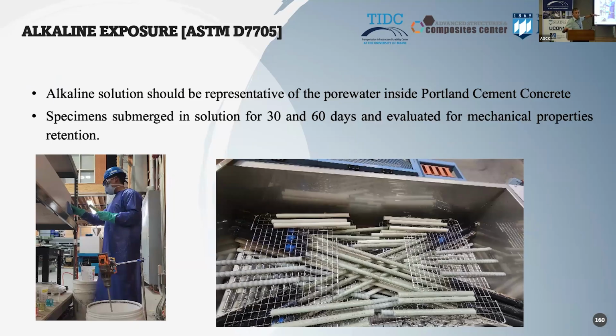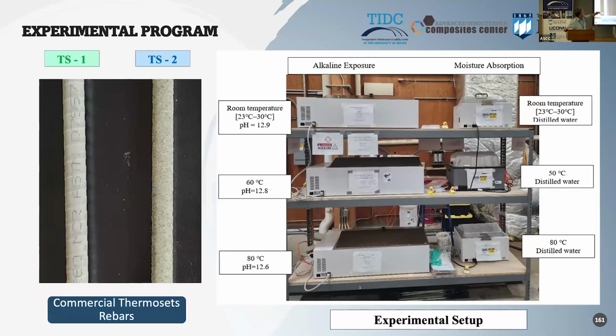So it takes quite a lot of planning in the lab in terms of having the right chambers, water circulating chambers that are set up at the right temperatures, and maintaining, in the case of the alkaline exposure, the correct pH. Again, a lot of work goes in terms of doing these durability studies, and they run over time, okay, as well. So again, I want to give you an idea of all the investment that this takes. Next. So in the experimental program, you have here a little bit of our setup. We have that rack with 6 chambers going on at the same time. In one set, we're doing alkaline. In the other one, we're doing distilled water.